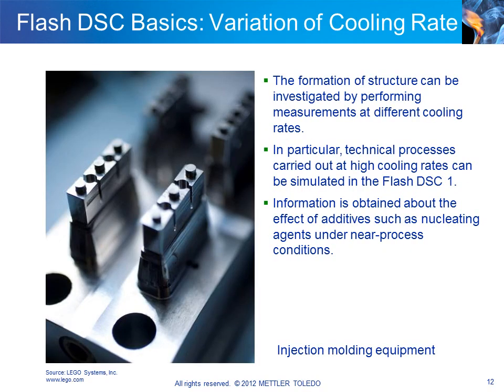The kinetics of structure formation can be studied by performing cooling measurements at different cooling rates. An important advantage of the Flash DSC-1 is that the cooling rates correspond to those of technical processes, such as those that occur in injection molding. This allows you to follow the formation of structure that occurs in the process. In addition, you obtain information about the function and action of additives, for example of nucleating agents, under near-process conditions. The data obtained from cooling experiments can be used to improve calculations based on models.